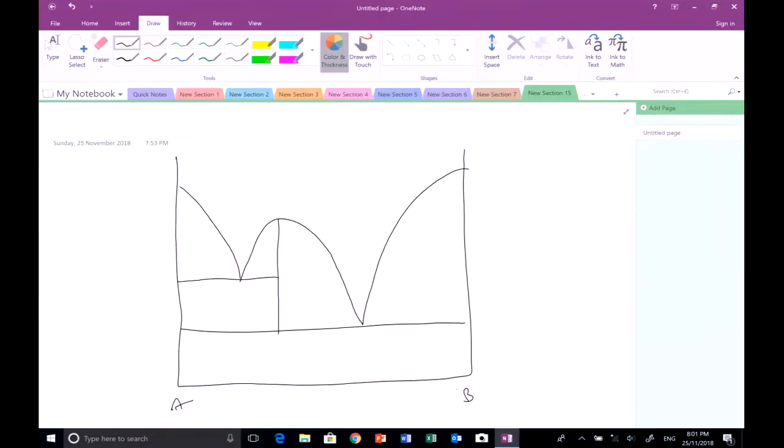And if you want mullite, the glass has got high silica, so they were adding alumina to drive the composition onto mullite because they wanted to make refractories from this. Very counterintuitive because glass is very bad as a refractory. And I said, you should have investigated the end members to start with. You've gone right on to the composition of mullite, and you've done exactly what everyone else does. You're not going to get any patents that way. So the very first experiment we did is what led to our patents, starting with pure fly ash.